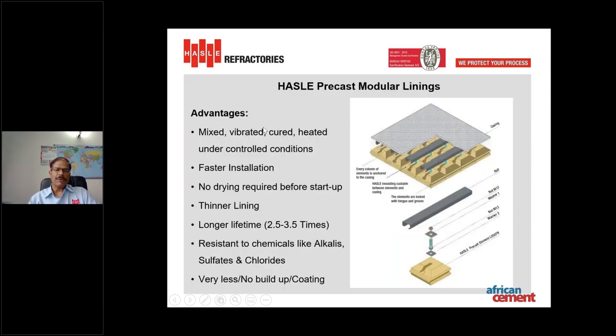Another product line is one unique precast modular lining solution, which is manufactured from our own castables in our factory. The basic advantage of this precast is that it is mixed, vibrated, cured and heated under controlled conditions in our factory. It can be installed faster than low cement castable. As it is already dried, you do not need to dry the refractory lining.